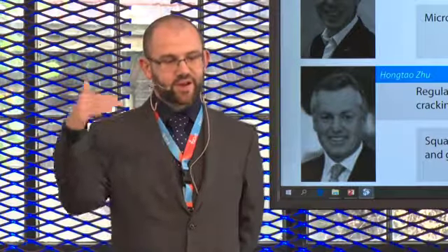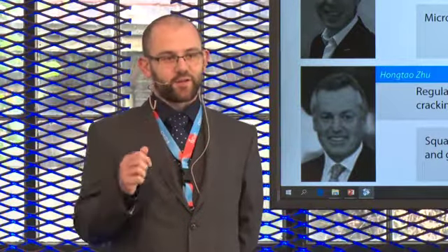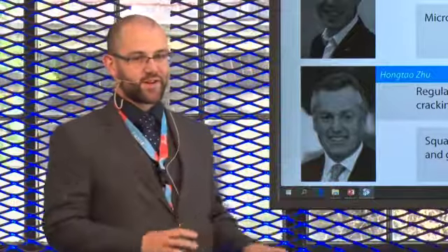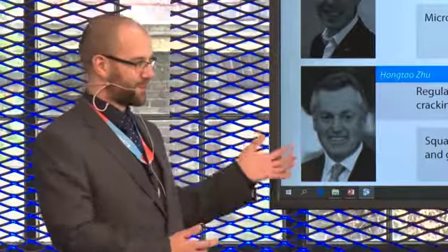The only plastic deformation I usually see is when a crack is so acute that it thins out the surface, you might get a little bit of plastic deformation, but generally it's quite remarkable how little deformation there is on the surface. So it doesn't appear to have ratcheting. From the few samples I've seen, I'll just clarify, these are the only 3 samples I've ever looked at, so it's a limited answer.